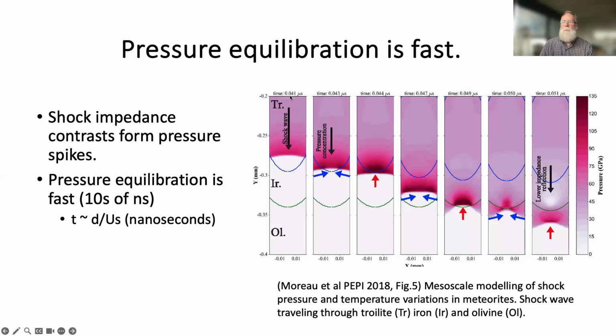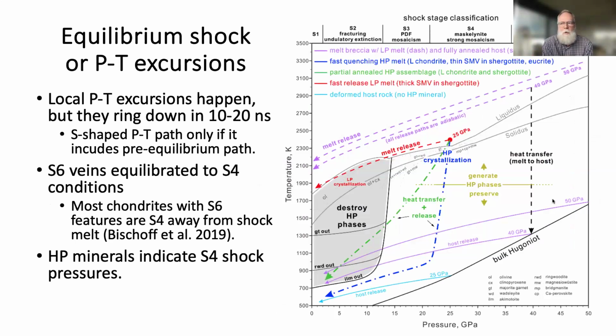But what I want to point out is the time. This time is basically 41 nanoseconds, and this is 51 nanoseconds. This entire thing equilibrated in 10 nanoseconds. So the time scale of pressure equilibration is on the order of tens of nanoseconds. The time scale of the thermal equilibration is on the time scale of hundreds of milliseconds. And so we create these things, we create local hot zones, the pressure equilibrates very quickly, and then we quench on a larger time scale to produce what we see. So the local PT excursions happen, but they ring down in 10 to 20 nanoseconds. But here's one possibility.